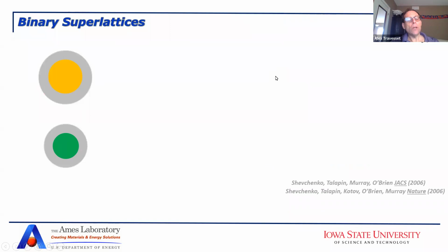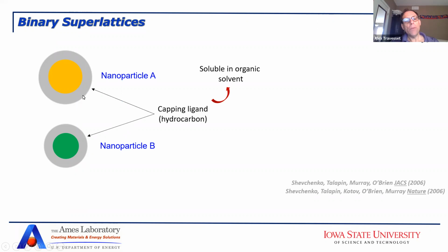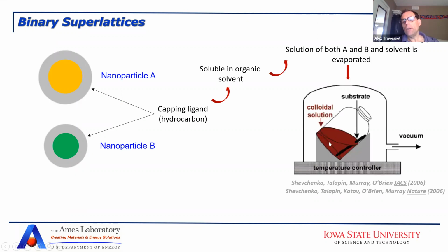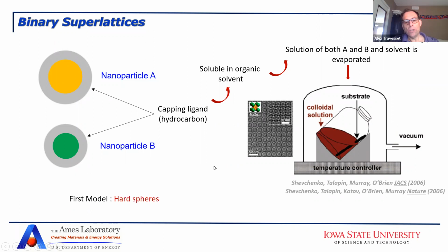So what is the problem that we are describing? We have binary nanoparticles. We have two types of nanoparticles, nanoparticle A and nanoparticle B. They are functionalized. There is a capping ligand that you attach to them. They are soluble in organic solvent, and then you put them together like this, and you just gradually, very slowly evaporate the solvent. In this way, you end up with a superlattice, which is binary. There are two types of nanoparticles, and this is an example. Sodium zinc 13 is one of my favorites. It has a very large unit cell with 112 particles in each unit cell.